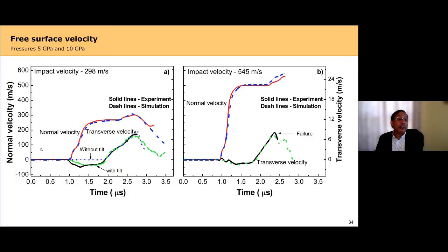If you look at the normal velocity, once again, I'm not going to go into the details. The normal velocity and the transverse velocity, once again, we can use our model to fit this extremely well. Having the transverse velocity, we are able to constrain the plasticity model extremely well. So this is at 5 and 10 GPa experiments. These are using steel anvils, so we are also using different anvils.